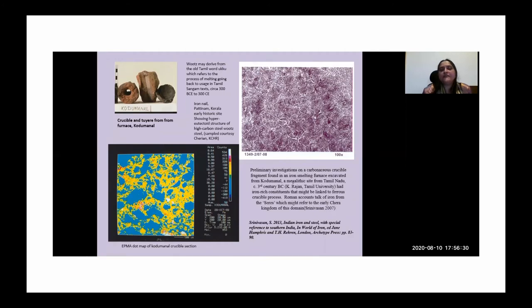And you can see there this typical hyper-eutectoid structure, which you also saw in the Mel-Sirivalur crucible, where you have this network of pearlite surrounded by prior austenite and surrounded by cementite grains. So even without doing the analysis, you can tell straight away that that is the typical structure of hyper-eutectoid steel. So it was already being certainly manufactured by this process by the early Christian era.